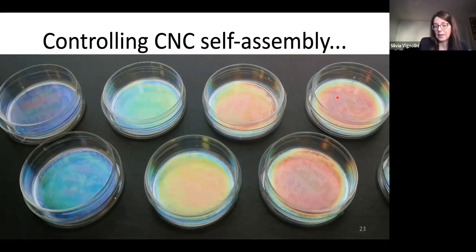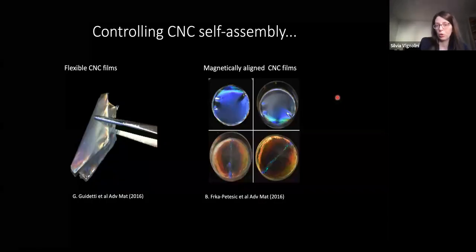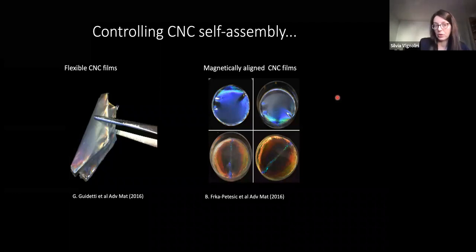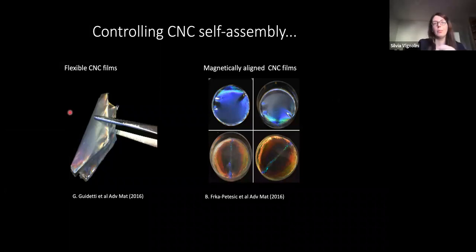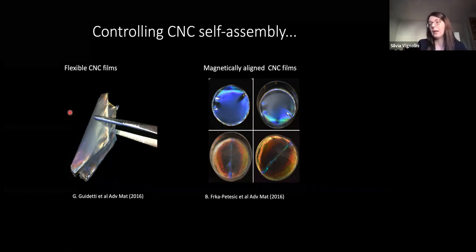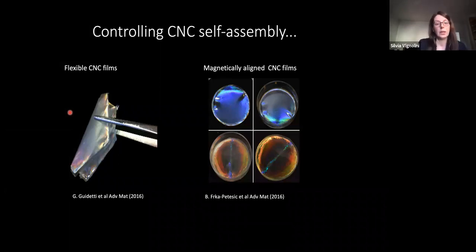In this case, we obtain film. But then if you want to change also, for example, the mechanical properties of this film to make it more flexible or more bendable or more elastic, then you simply need to add additional material, a polymer like PEG. Here in this case, we just show that the presence of a surfactant can completely change the mechanical properties. But many people have shown and demonstrated that using many other different types of polymer, you can completely change the mechanical response of the film, but at the same time maintain this nice coloration.